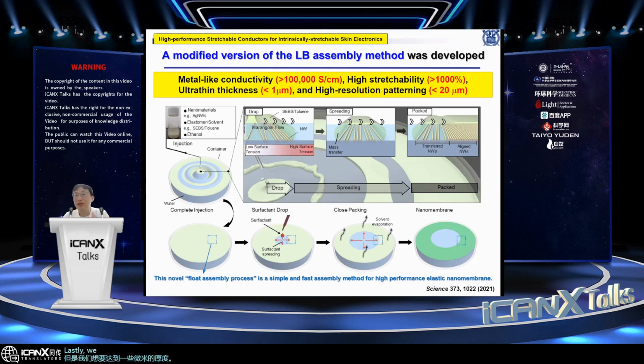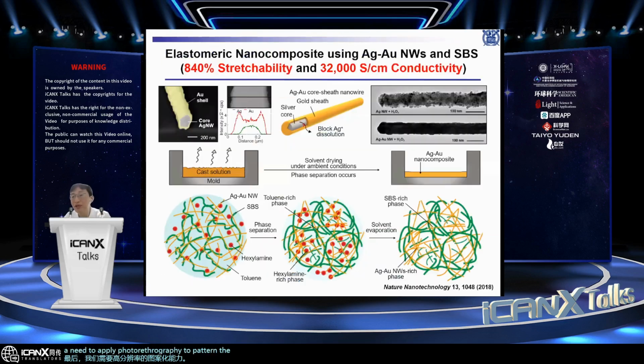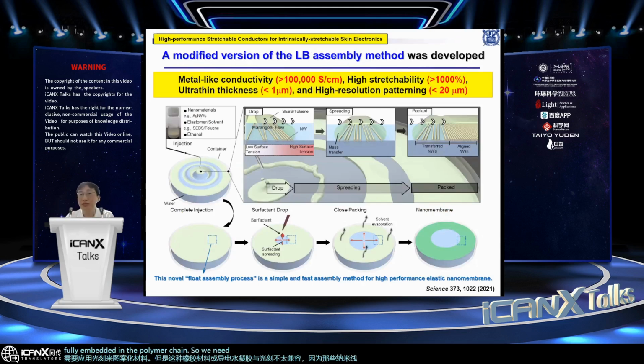Lastly, we need high resolution patterning capability. That means we need to apply photolithography to pattern the material. But these rubbery materials or conductive hydrogels are not very compatible with photolithography because those nanowires are fully embedded in the polymer chain. So we need a new material structure to apply photolithography and to pattern the material with high resolution. So it is very challenging to achieve all these requirements at the same time, but these requirements are needed for a stretchable conductor to make high performance intrinsically stretchable skin electronics.